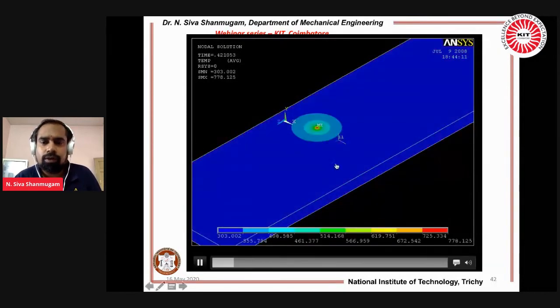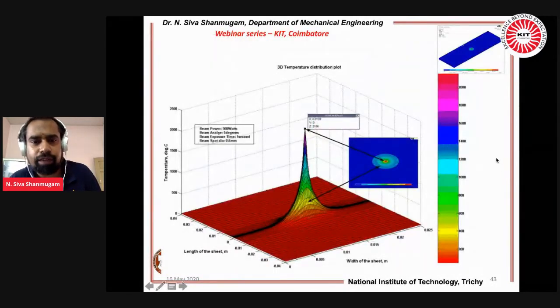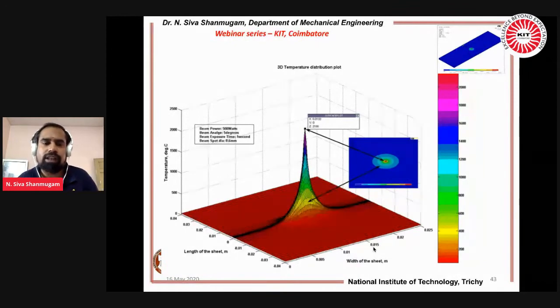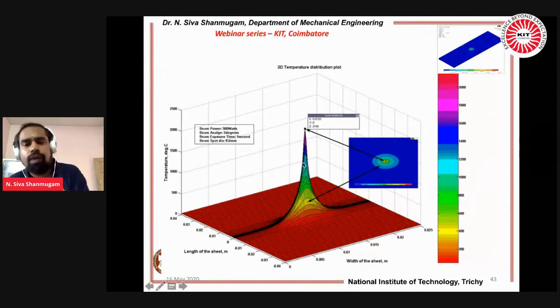Okay, so once again I'm replaying the video. You can extract, because you can couple with an Excel sheet, or you can couple with MATLAB, and you can plot how the temperature is distributed for a single spot, because we are doing only matrix manipulation. So this is the geometry of the sheet. It is something around 50 mm length and 100 mm width, a rectangular sheet. So you can feed the information into your MATLAB code, and you can find out the peak temperature